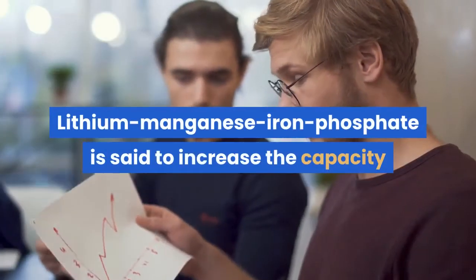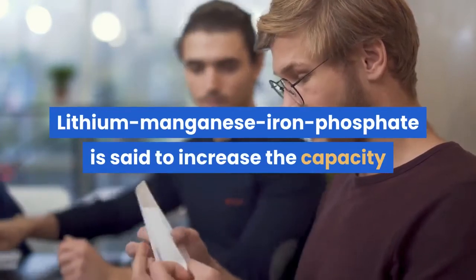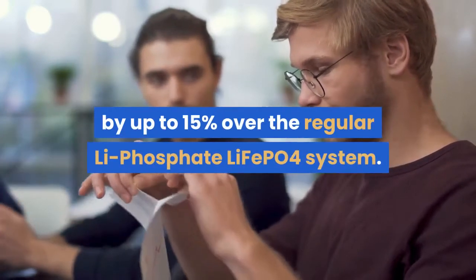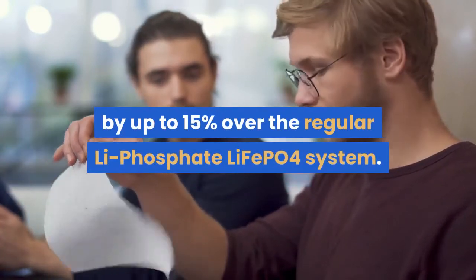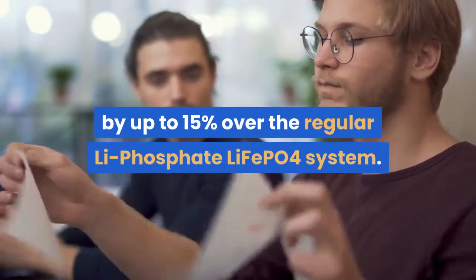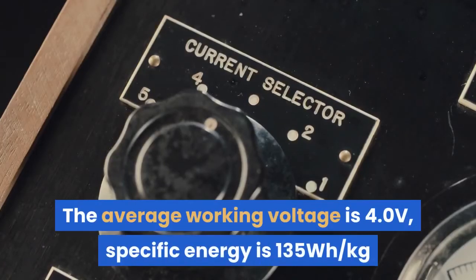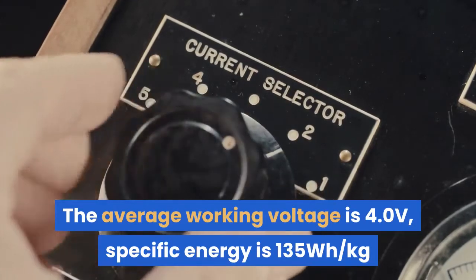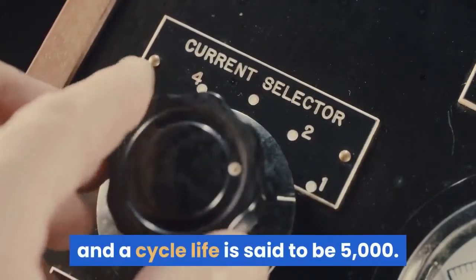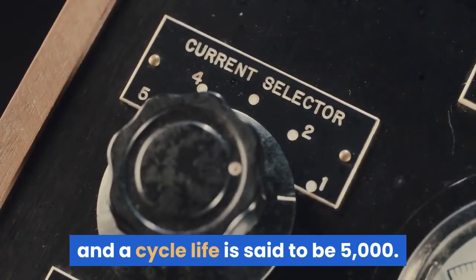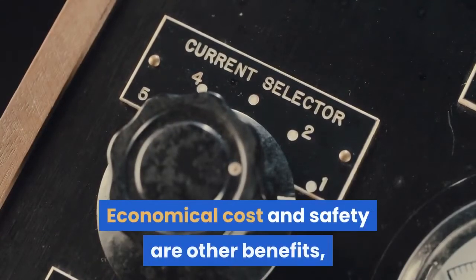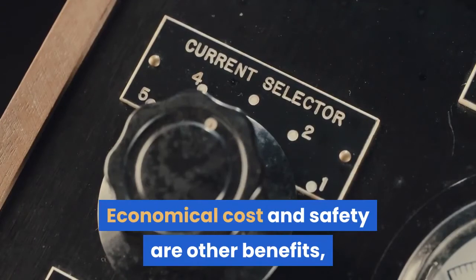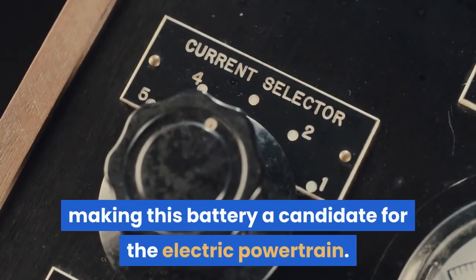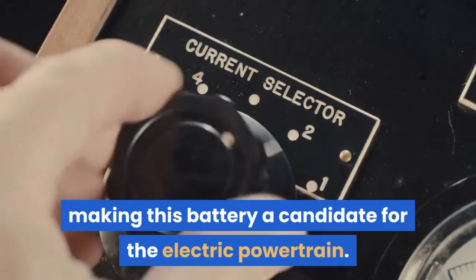Lithium manganese iron phosphate, LMFP. Lithium manganese iron phosphate is said to increase the capacity by up to 15% over the regular Li-Phosphate LiFePO4 system. The average working voltage is 4.0 volts, specific energy is 135 watt-hours per kilogram and a cycle life is said to be 5,000. Economical cost and safety are other benefits, making this battery a candidate for the electric powertrain.